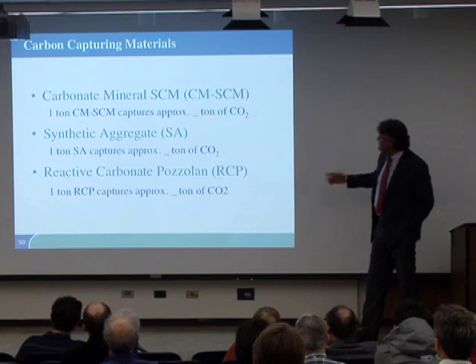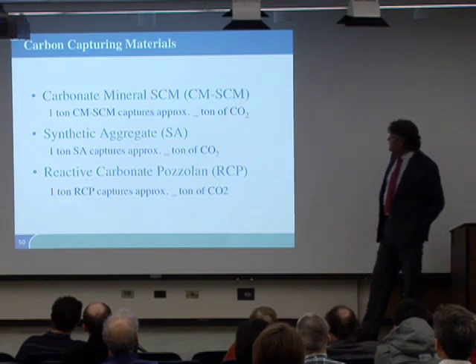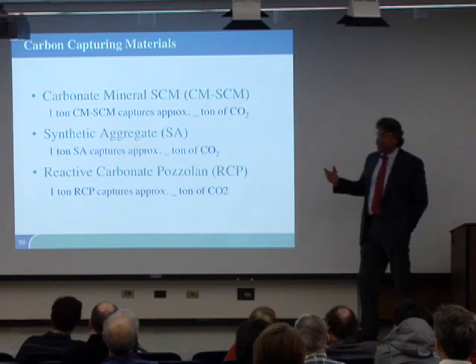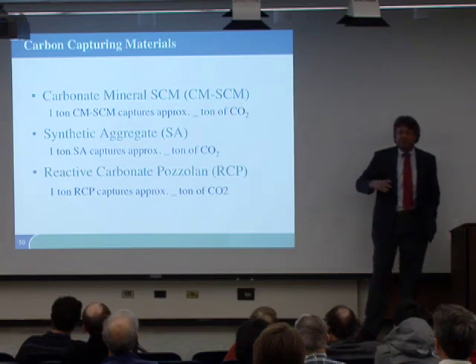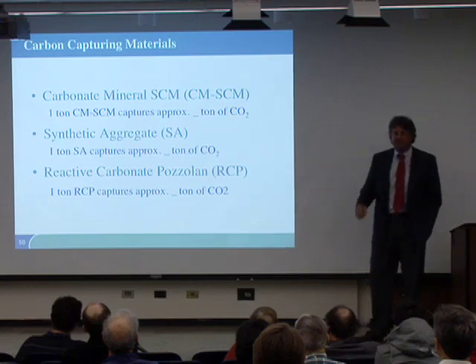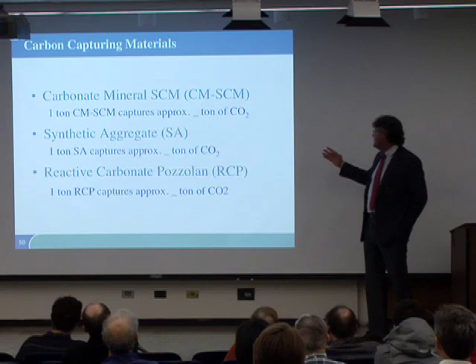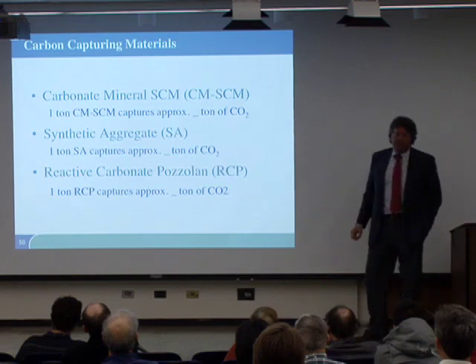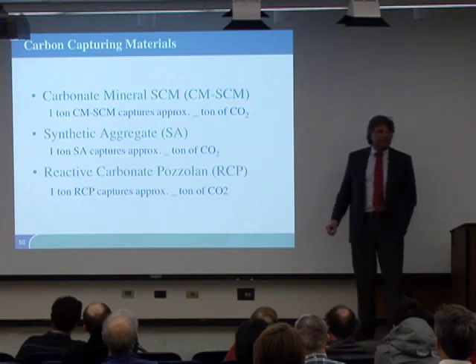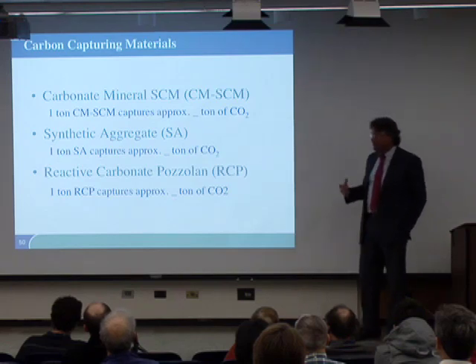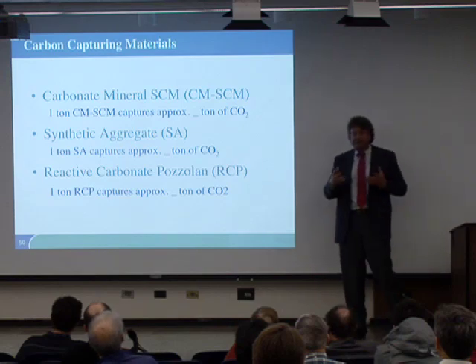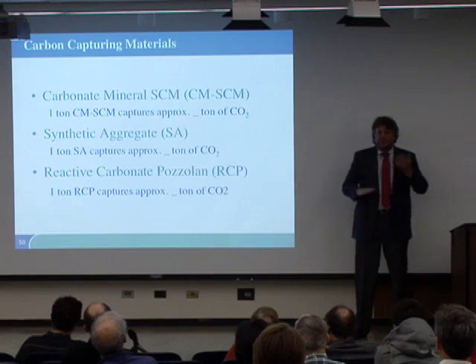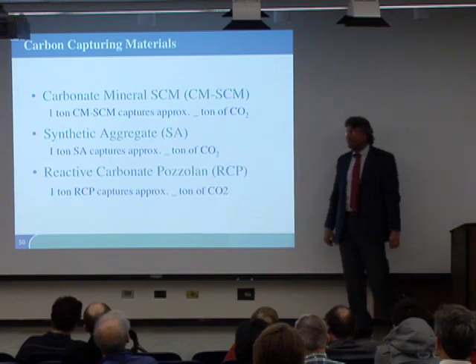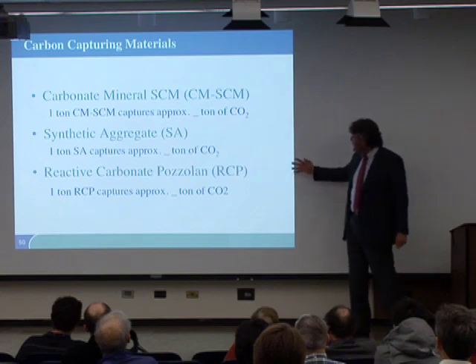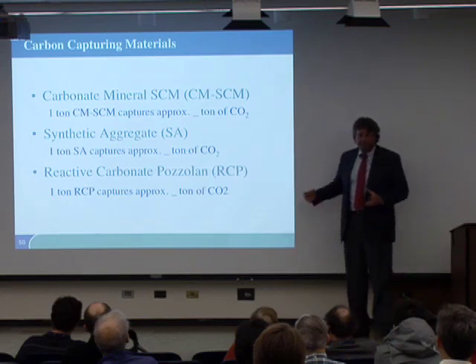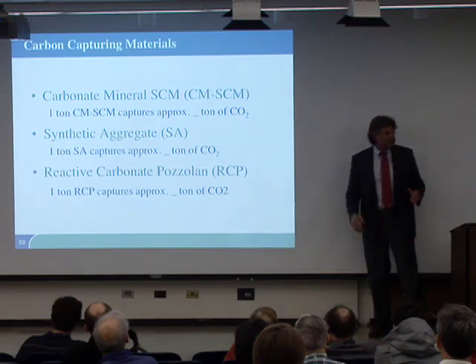And we're also making a material called the pozzolan, which is named after the city of Pozzolana near Mount Vesuvius, where the Romans put the first fly ash and limestone together and sintered it to make the first Roman cements. Pozzolans are, if you're building a very high skyscraper and you need very high strength cement, you would add a pozzolan, which has a lot of amorphous silica in it and dissolves in the high pH of the cement and gives you coherent grain boundaries and lowers the permeability and gives you very high strength. And at the locations where we're mitigating fly ash in addition to making cement, we incorporate that into the cement and it makes a great cementing material.